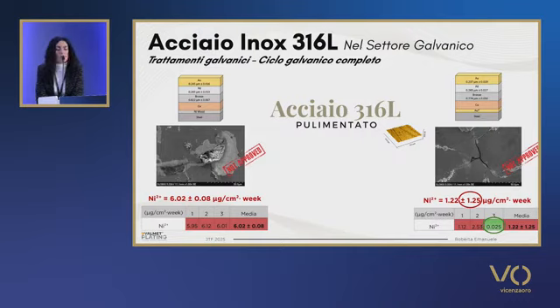Based on this study, we may say that our assumption that there was a nickel dispersion in the intermetallic phase was wrong, because the time since the preparation of the sample and after the week of release is not enough to enable nickel to get across the galvanic coating.